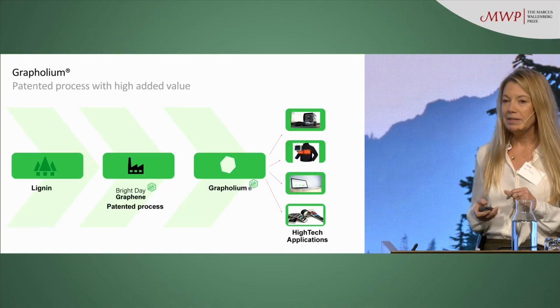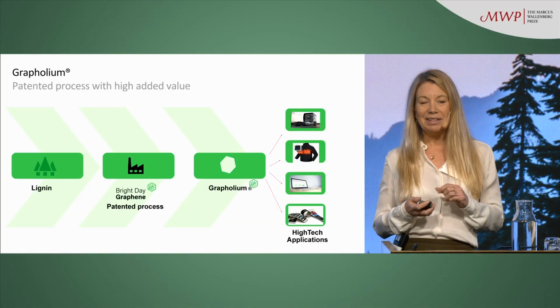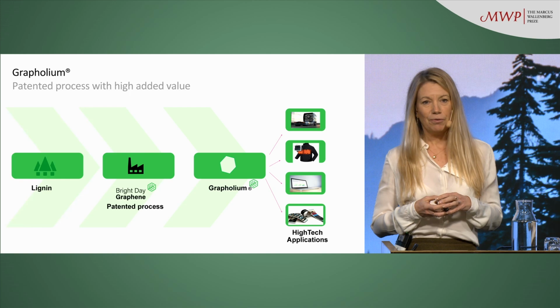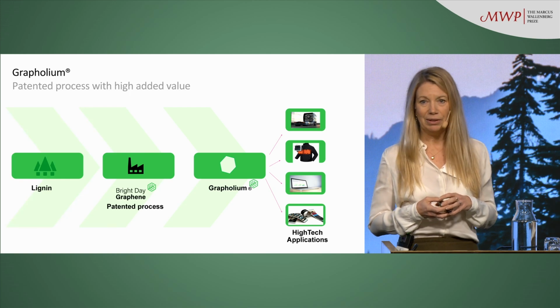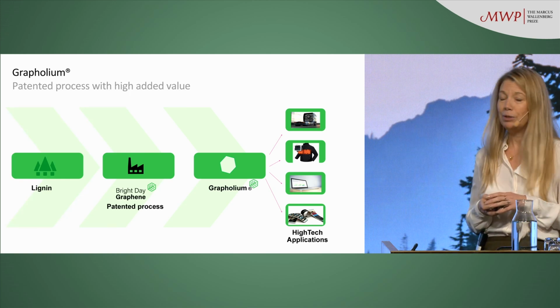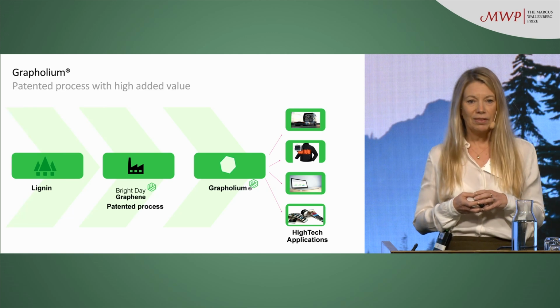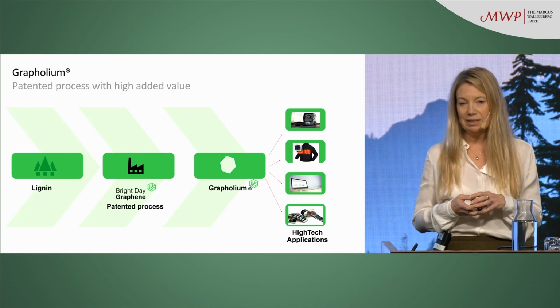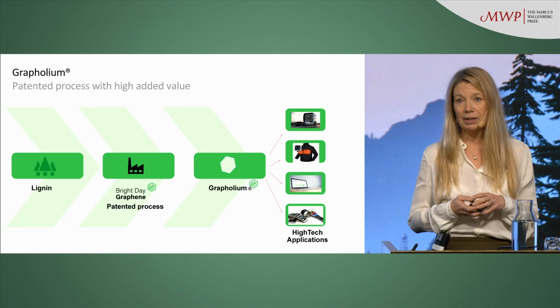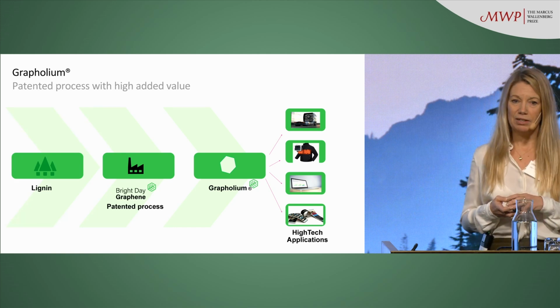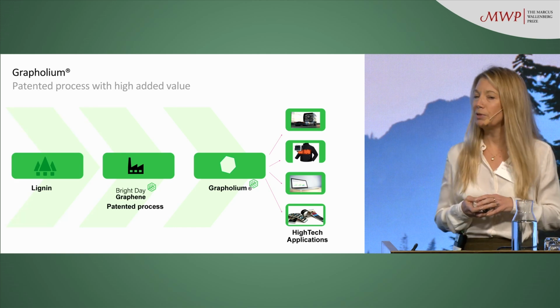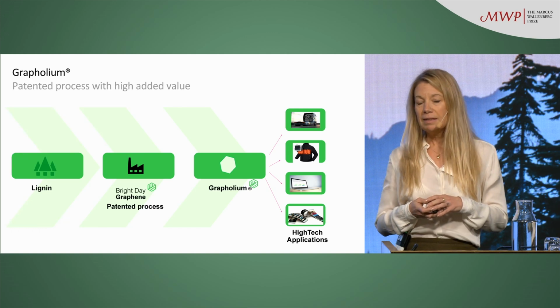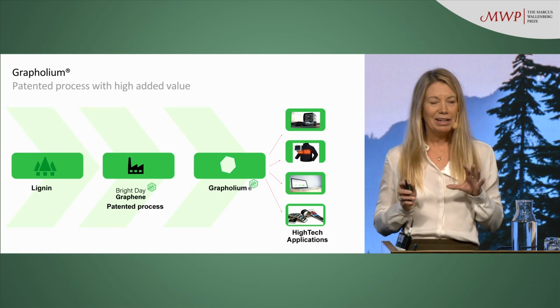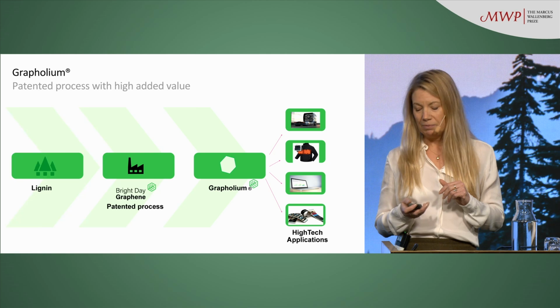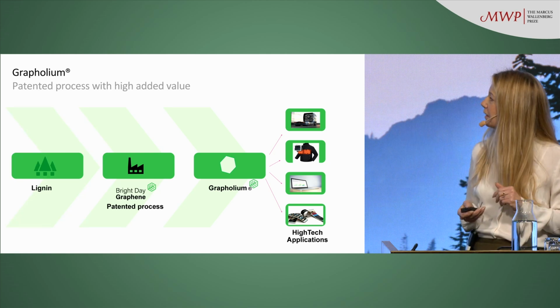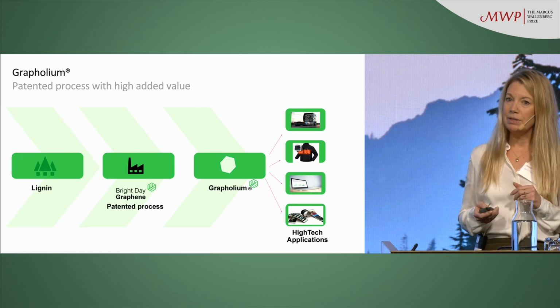So we developed this process that we patented, where we transform lignin into a graphene powder that we call grapholium, that has the large thin flakes that gives us better conductivity and makes it suitable for the high-tech applications, like energy storage and electronics. And this is a high value-added process. Graphene is adding a lot of value to these products.